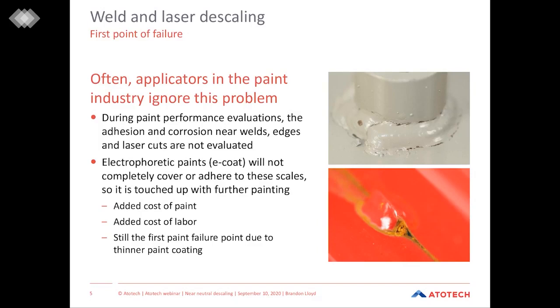Looking at the right side of this page, you can see in the top image some of the silica inclusions along the edge of the weld itself, where we have very poor coverage of the E-coat paint. And then the image on the bottom is a part that had been E-coated and then wet painted. And you can still see, even with the addition of the wet paint, that the weld joint area is still the first point of corrosion.